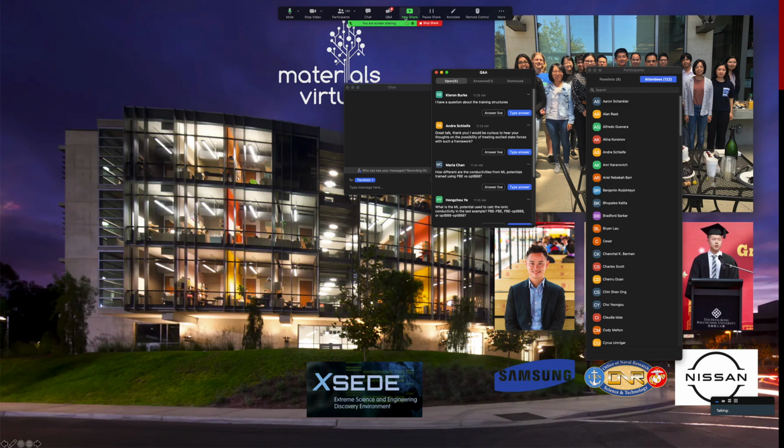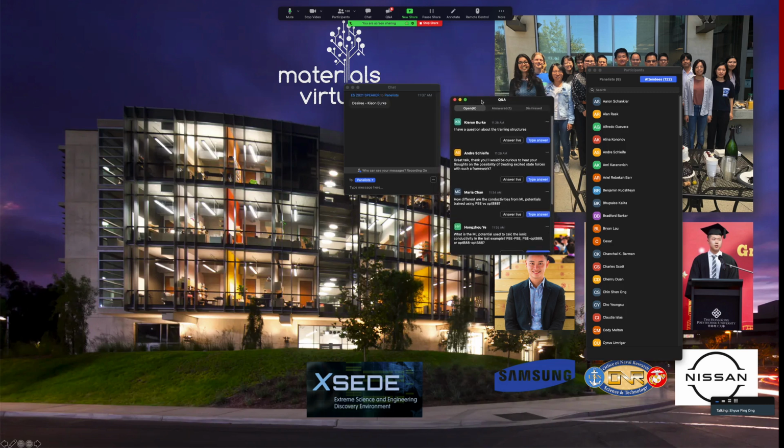In other words, I would say that anything that your electronic structure method can do via first principles, you should be able to do via machine learning interatomic potentials, as long as you do not go too far out of bounds, right? The main things that you can't do are, for example, if there's a lot of electron transfer occurring and you are trying to simulate reactions happening. Given that your machine learning interatomic potential doesn't treat electrons, you're not going to have a lot of luck doing that, right? So I think that's the answer.